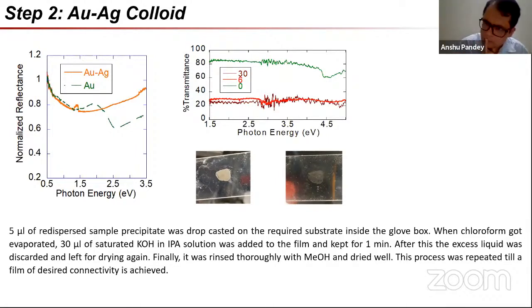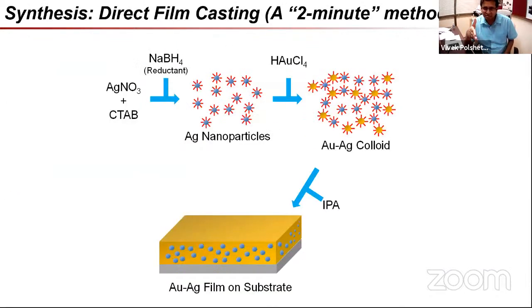What I understood is your gold precursor is HAuCl4, right? Yes. So, let us say you have a very small silver nanoparticle formed in the first step. Is it not possible that the chloride of HAuCl4 will react with silver and form some sort of silver chloride, which is again insoluble in water, and then some of the gold gets trapped in there, and that can have at least a similar EDX line map? Absolutely, that is very possible.